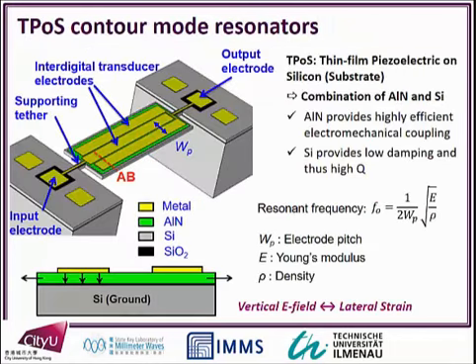So how do these actually work? We're looking at what we call contour mode resonators. They are 2D resonators. You stick these metal electrodes on the top, then you've got the piezoelectric, and then the silicon, which is grounded. You put a voltage on the top electrode, and that drops a field, and through the reverse piezoelectric effect, that generates a lateral strain, and that drives the mode in the width direction. So these modes are vibrating laterally. In this case, it's vibrating along the width.